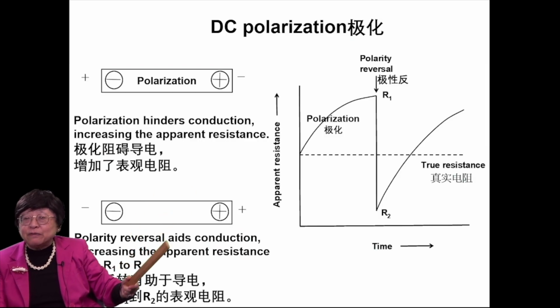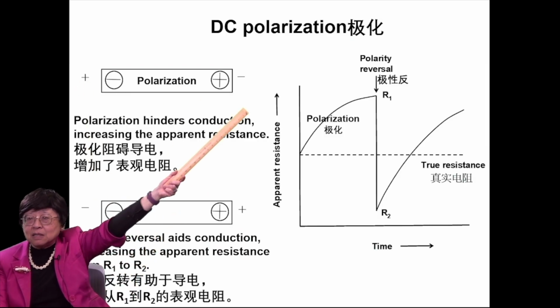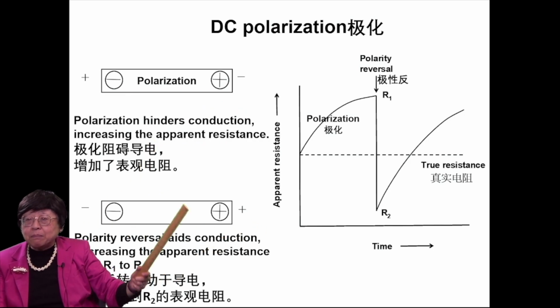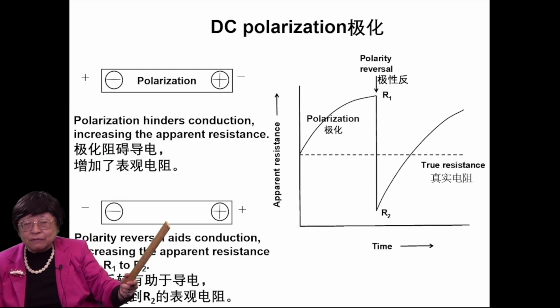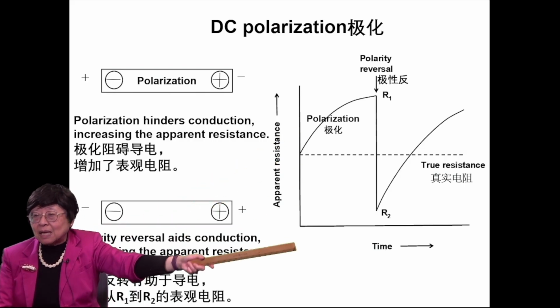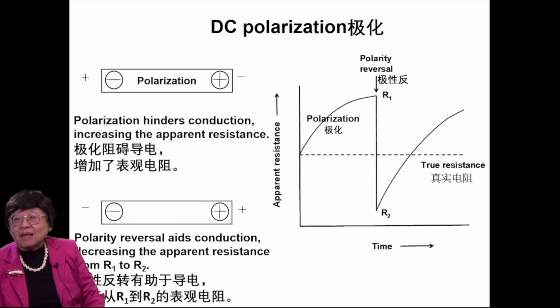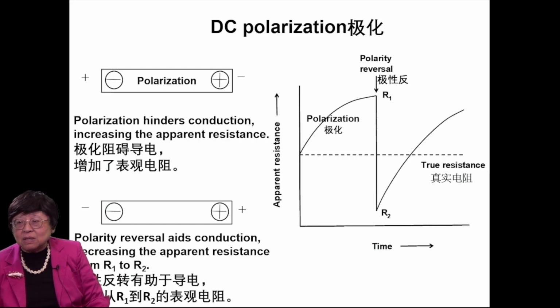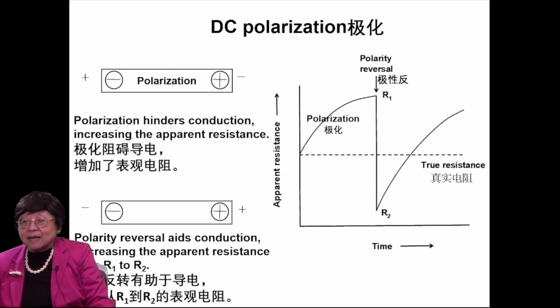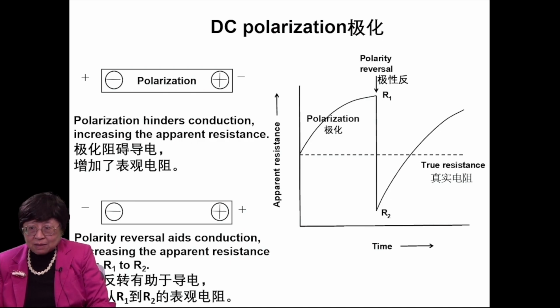However, if one suddenly reverses the polarity, so plus, minus, now reverse to minus, plus, the polarization cannot instantaneously revert in polarity, so it stays. So now the polarization aids conduction as opposed to hindering conduction. As a result, the apparent resistance goes down suddenly from R1 to R2. Okay? R1 is above the true resistance, R2 is below the true resistance. So one can have a means of looking at polarization through resistance measurement. And in this case, it's not the true resistance, but the apparent resistance.